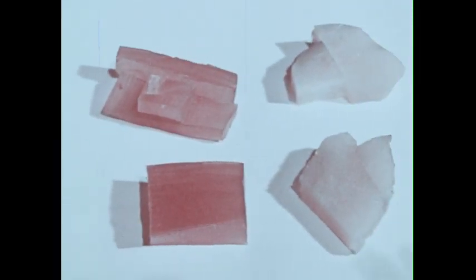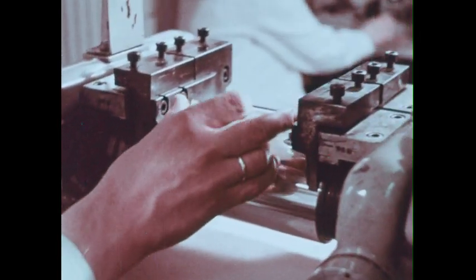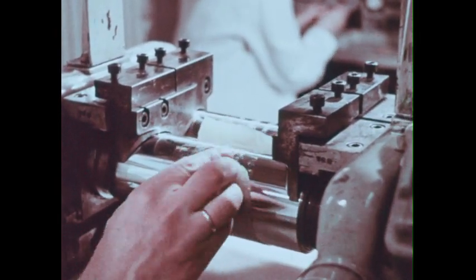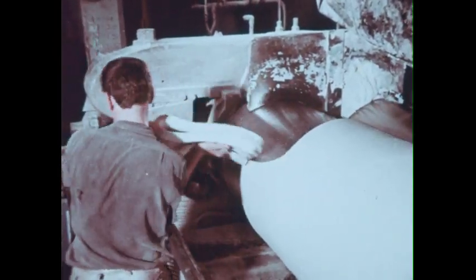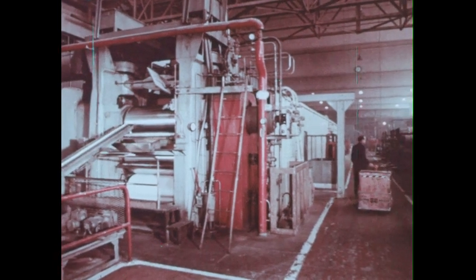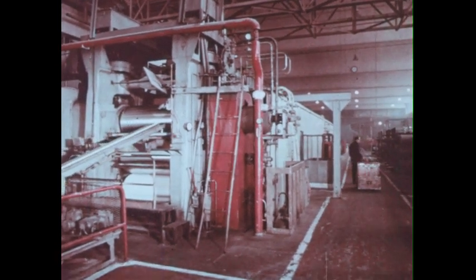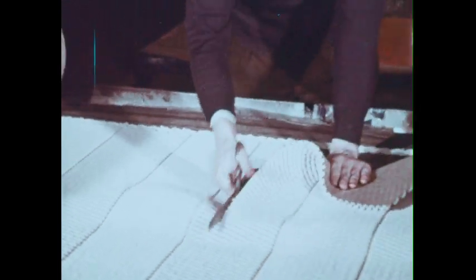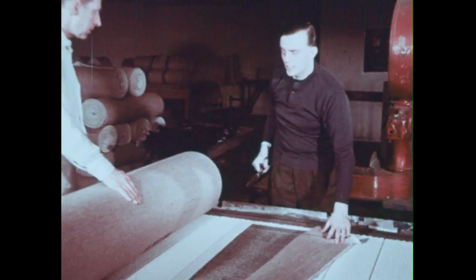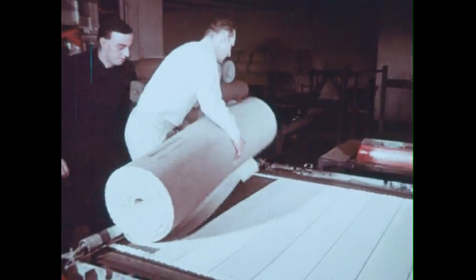Once we had samples, we could study their properties. The weight of this one was particularly low. It behaved well on the mill and broke down much faster. This new styrene butadiene rubber cut mixing times by as much as 20%. Throughput to the calender and curing chamber was now fast enough for the whole plant to be run at maximum efficiency. The manufacturing problem had been solved, and we gained valuable information on the control of polymerization.